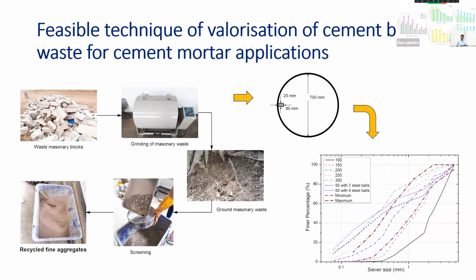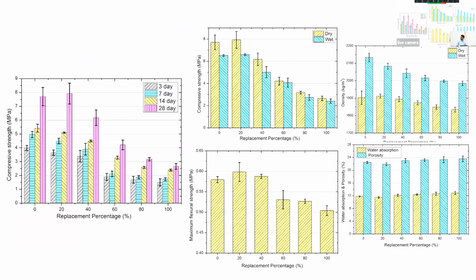So these are some findings about the mortar properties that they have developed and the comparison with the normal mortar. Here also you can see the main one is the strength. Up to 40%, we can replace the normal aggregate using these recycled aggregates. It means we can save the resources which are available, because we have limited resources at the moment. So we need to think about saving the available resources as well. In addition to that, several other properties: the compressive strength, the dry and wet strength, density, flexural strength, water absorption and porosity. To some extent, like 20%, you can see the enhancement of the properties as well. So most of the mechanical properties have been enhanced with these recycled materials.